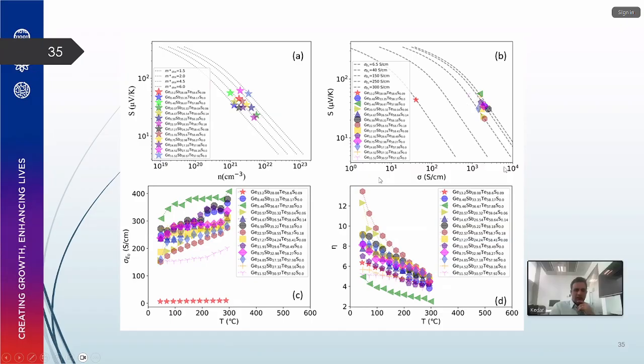Why does one sample sit so far away? No, there are 16 samples here. No, in the Jonker plot, the stars. This is the first sample. The rest of the samples are here in that region. I just plotted the Jonker at different sigma-zeros. So this sample was bad somehow. But once you introduce more and more antimony telluride, the curve shifts and the values of sigma-zero increase. So the highest power factor has the highest sigma-zero, and the highest ZT also.